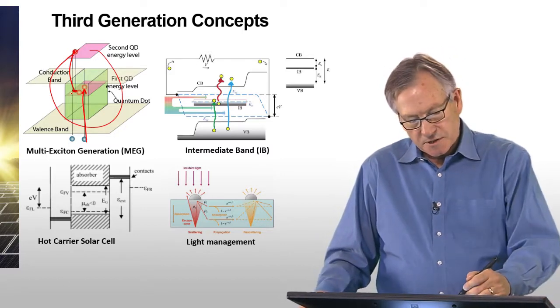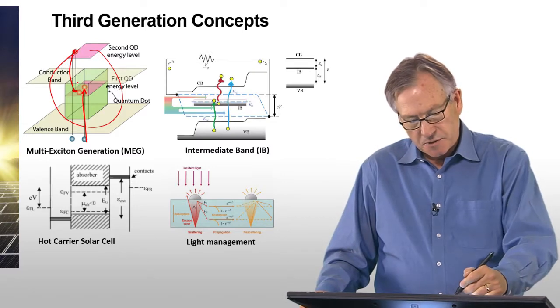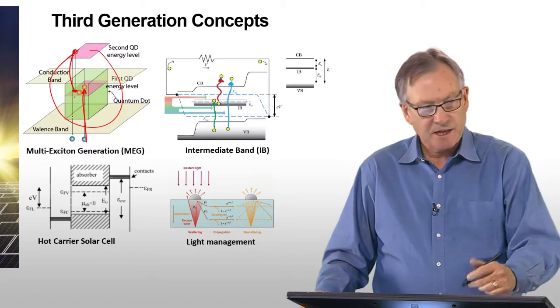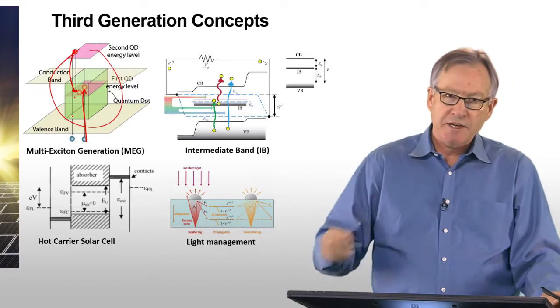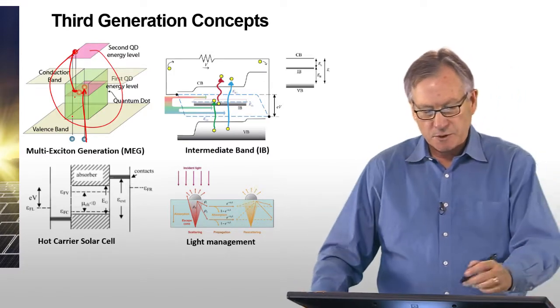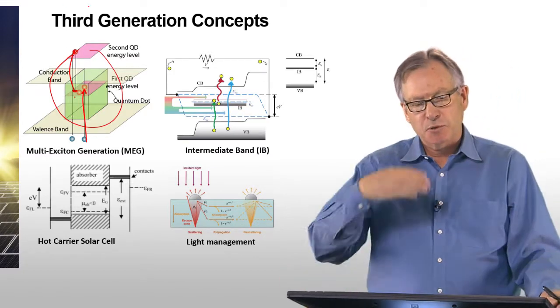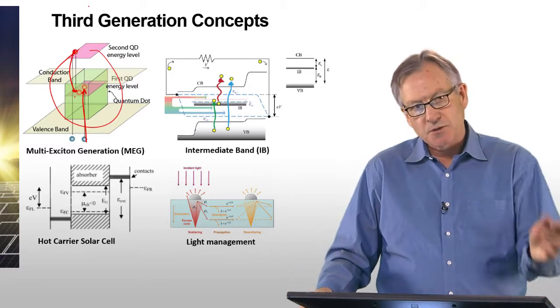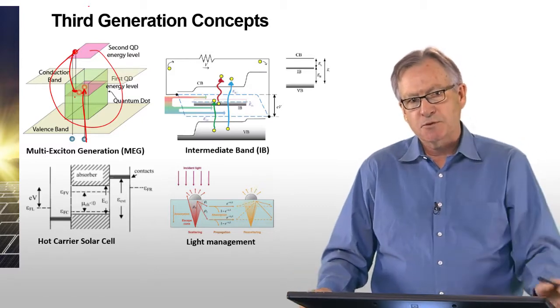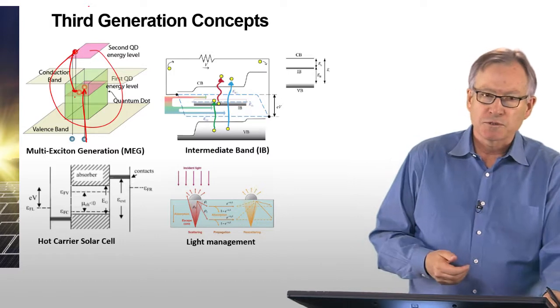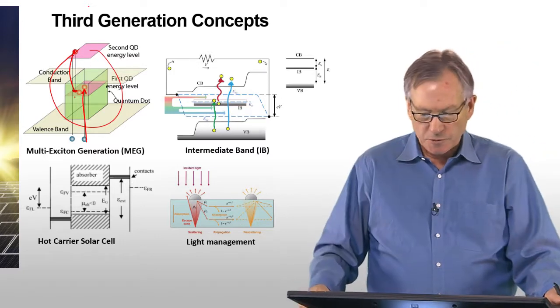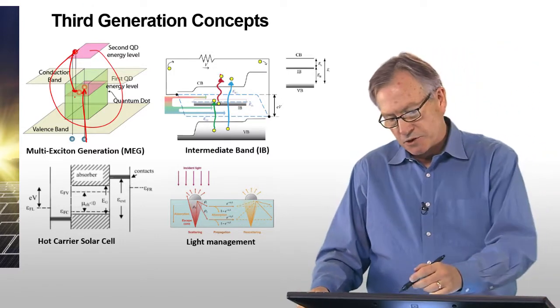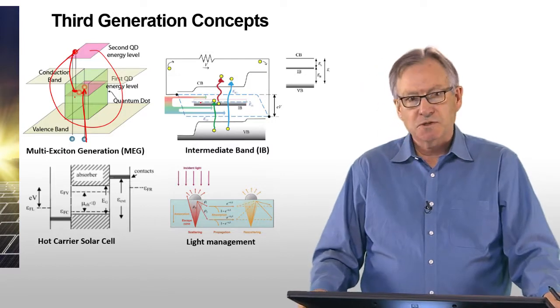And it requires then that this energy between this level and this level be twice the band gap. So once it's twice the band gap, you can create 2 electron hole pairs. If it's 3 times the band gap, you can create 3 electron hole pairs. And in this way, you have a quantum efficiency that's greater than 1, and the overall conversion efficiency can be greater than 33%.